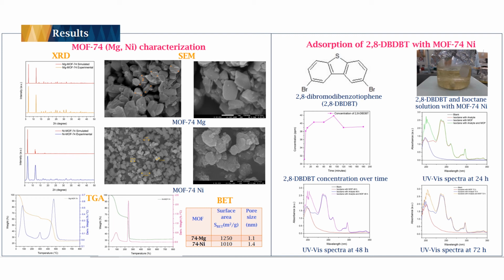in here. As one can see, there is not really any difference between the three spectra, be it 24 hours, 48, or 72. The three of them are almost identical. The isooctane with analyte and MOF didn't have any difference between times. Thus, it was concluded that even at 72 hours, there was no adsorption of 2,8-DB-DBT by the MOF74 nickel.